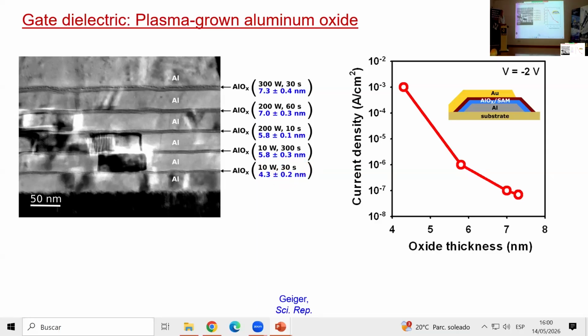And then why do you choose this way of having aluminum oxide and not, for example, ALD or other thing? The main reason is that we cannot pattern the dielectric if we deposit it by atomic layer deposition. When you deposit by atomic layer deposition, the aluminum oxide will go everywhere. Here, the oxidation, the advantage is that the aluminum oxide will only oxidize the aluminum gate electrodes, but it will not oxidize the rest of the substrate. And so we don't have to go back and pattern it.